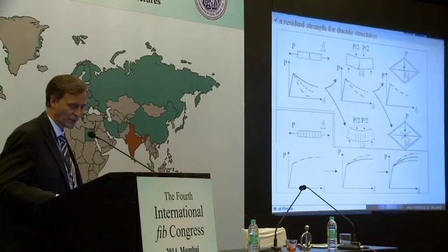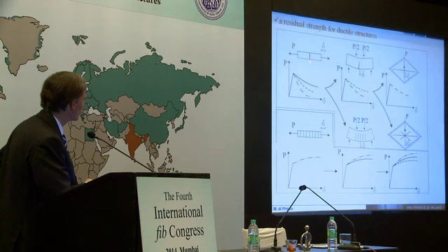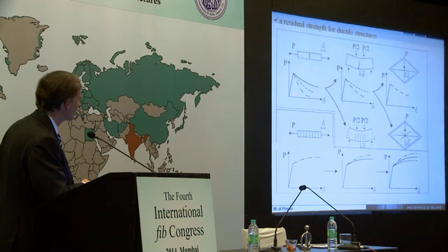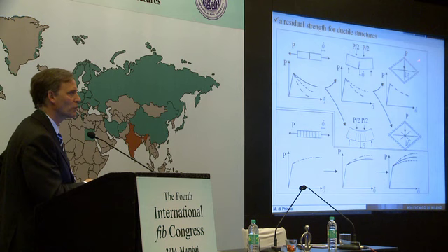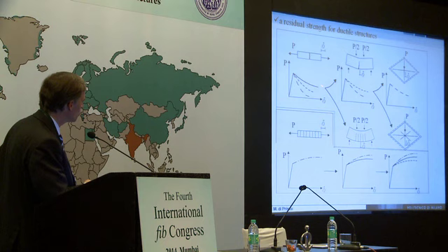So we proposed as a starting point this graph that highlights how you can have in uniaxial tension with only fiber reinforced concrete material different trends after the main first cracking, if you like. And according to the softening, you could have, increasing the redundancy, a different behavior. So for instance, if you look here, you have three lines, the solid one is the best. And you see that the solid one, when we pass to bending, becomes hardening here.